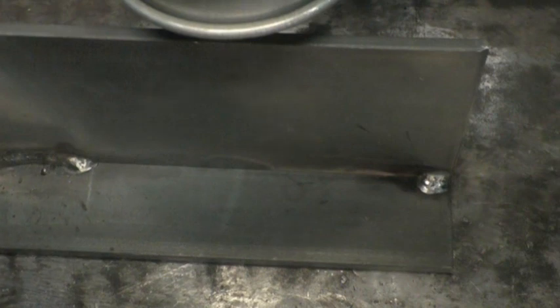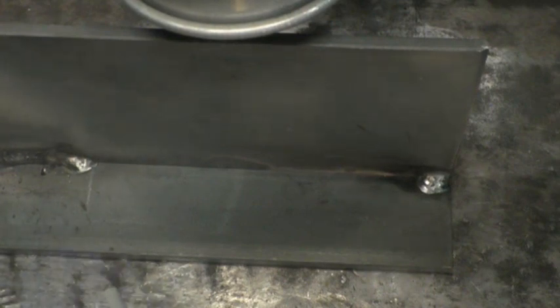You can get away with that with MIG welding. You can get away with that with certain stick electrodes, 6011 being one of them, but it's not something you want to do with 7018. So again, I'll show you the maximum that I would ever manipulate the puddle with a 7018 electrode here. And this is in the horizontal position. In the true flat position, you could get away with a little bit more. So I am consciously moving that rod up and down.